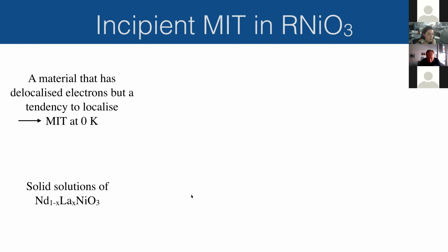So what we proposed was that you should probably try to make a mixture of two different nickelates. So what we did was a solid solution of neodymium and lanthanum nickelate, lanthanum nickelate being metallic, neodymium nickelate being insulating. And like that, you should have a propensity to disproportionate, but you should have enough itinerancy of the electrons to stay conducting. So the idea was that you should maybe try to find a metal insulator transition that is occurring at around 0 Kelvin.